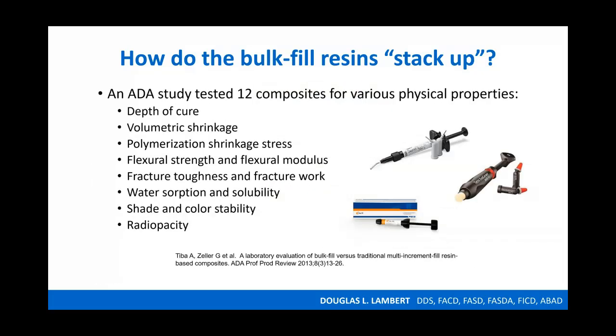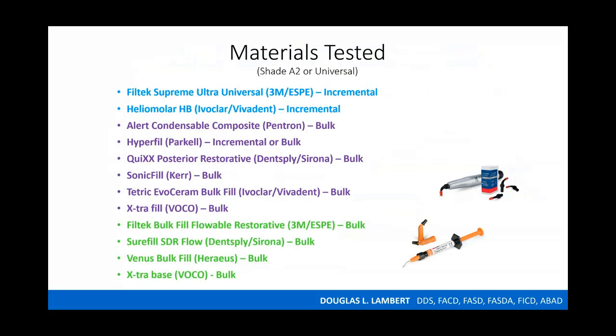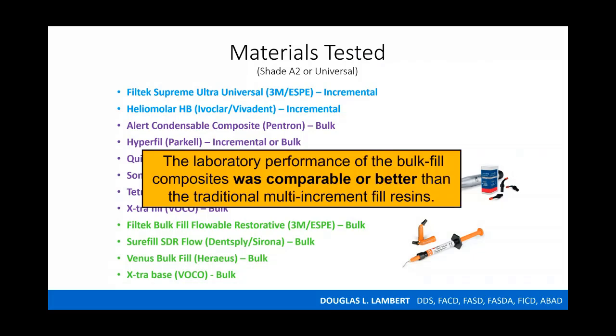And this was a great study by the ADA where they really took the next step on some of the studies and looked in-depth at 12 different composites based on their physical properties. Looked at things like depth of cure, volumetric shrinkage, flexural strength, water absorption, shade and color stability, and radio opacity. And they compared these 12 composites, 2 basic incremental paste type composites, 6 bulk fill body or paste type composites, and 4 flowable composites that are bulk fill in nature as well, and just compared them, toe to toe, head to head. And what did they find were the results on this? They came back with their conclusion that the laboratory performance of these bulk fill composites was comparable or better than the traditional multi-increment fill resins that we've been using. So the materials are definitely standing up to this bulk fill and semi-bulk fill technique.